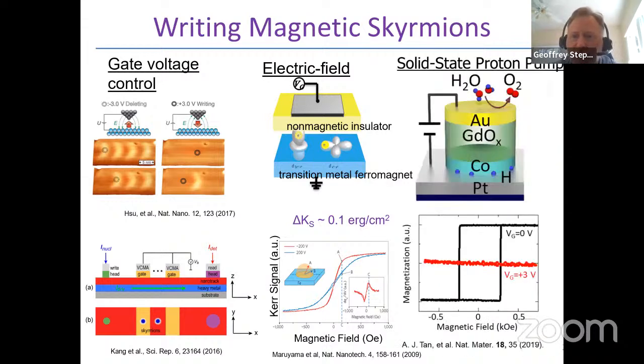We have discovered subsequent to that we can use other ions as well. Most interestingly, perhaps, is a proton. And in structures where one has a metal oxide metal stack, like in this case cobalt, gadolinium oxide, which is our gate oxide of choice, and gold at the top, by just applying a gate voltage in the ambient atmosphere of a couple of volts, that gate voltage is enough to split water, so just water from ambient humidity, and harness a proton that can be pumped through the gadolinium oxide, which acts as a solid state ionic conductor.